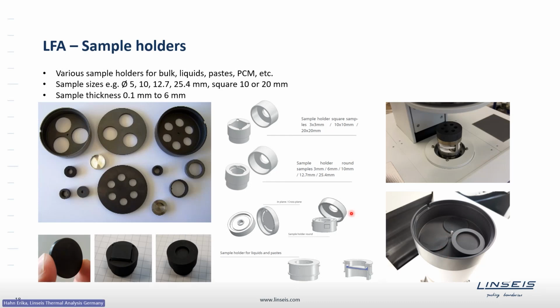So as mentioned before, the laser flash is also able to measure powders, liquids, or pastes. For that, we have the special sample crucible where you fill in your amount of liquid, for example, and then you just have a closed sample crucible. But also for the higher temperature range, we have here some excess volume on the sides so that the sample can expand during the measurement without spilling out of the crucible. And in the middle here, the sample thickness is well defined by the bottom and the lid of the sample crucible.